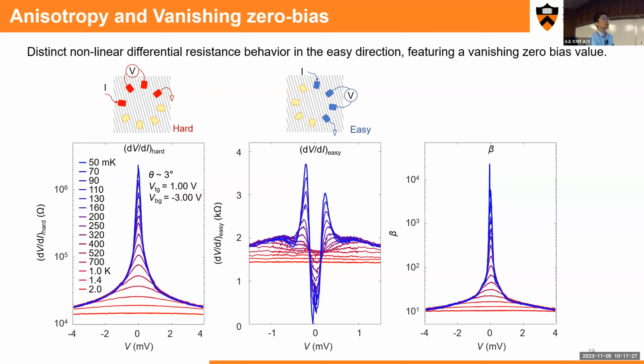And moreover, if it's a triplet, it's a completely different situation. But if it's like most of the superconductors we have seen, we have applied up to 8 Tesla out-of-plane magnetic field, and we still couldn't see this gap behavior getting killed. So we favor that this state is not superconductivity, but if we apply a higher field, we have no idea what's going to happen, and we should definitely explore that. Actually, if I remember correctly, the gap actually gets slightly bigger. Yes, exactly. Really nice discussion. Thank you.